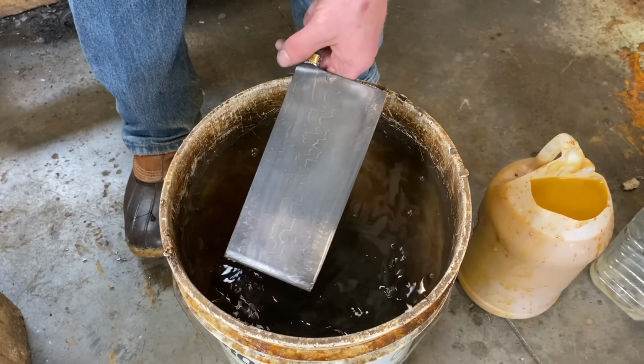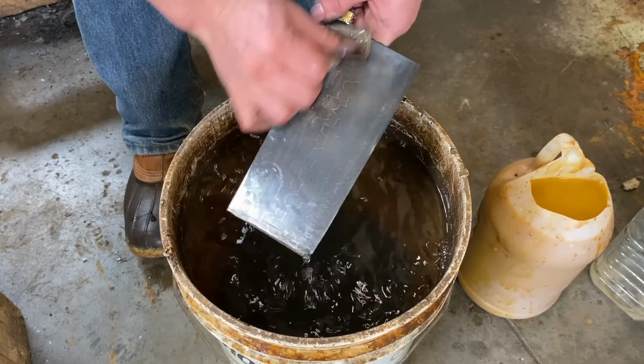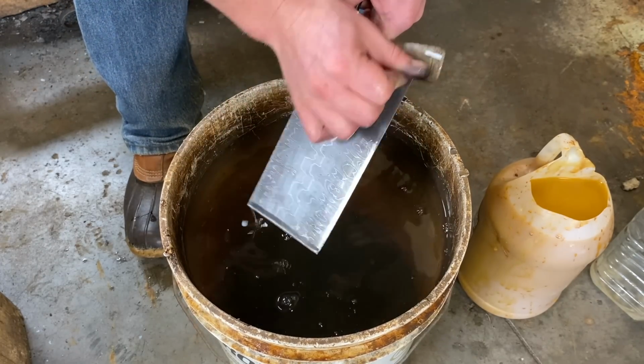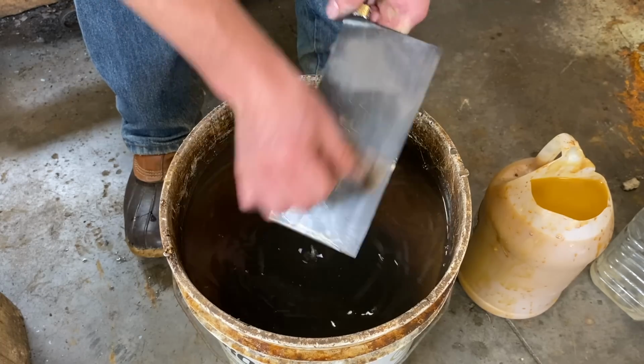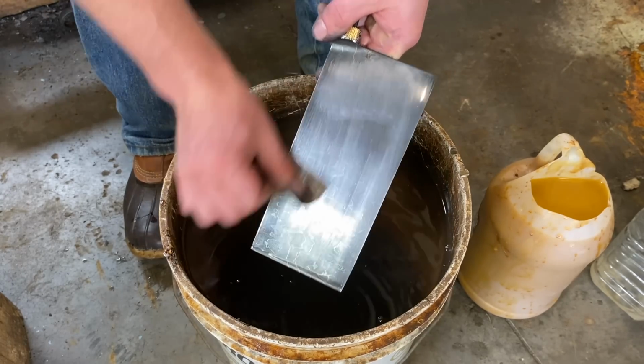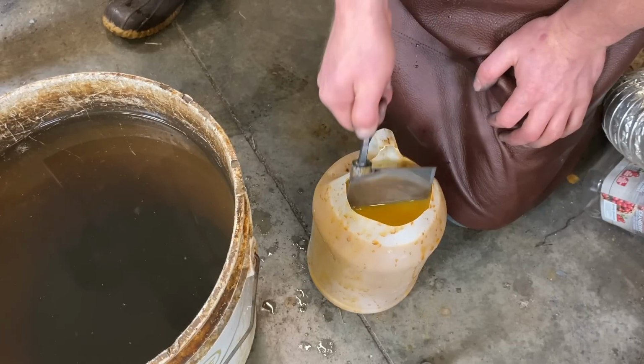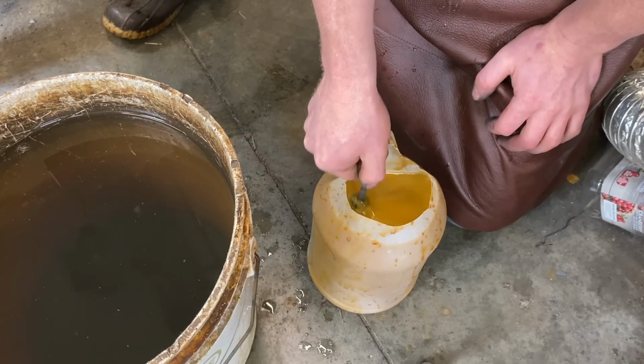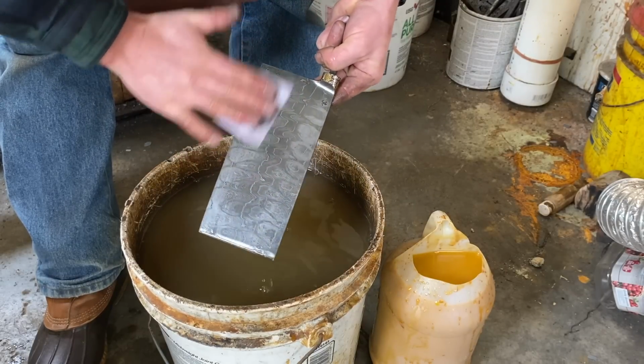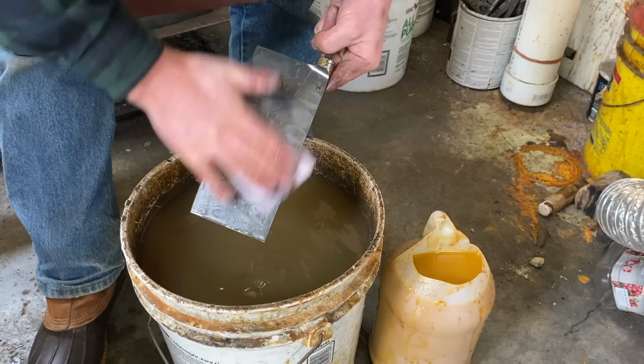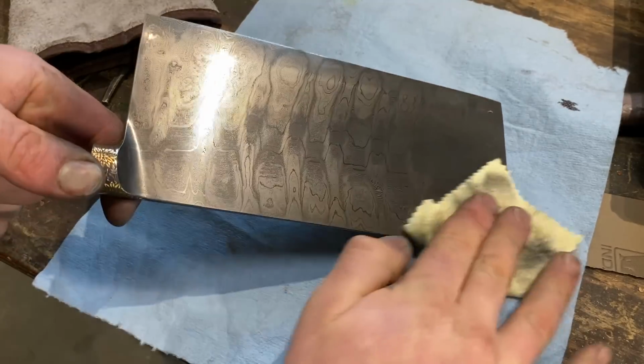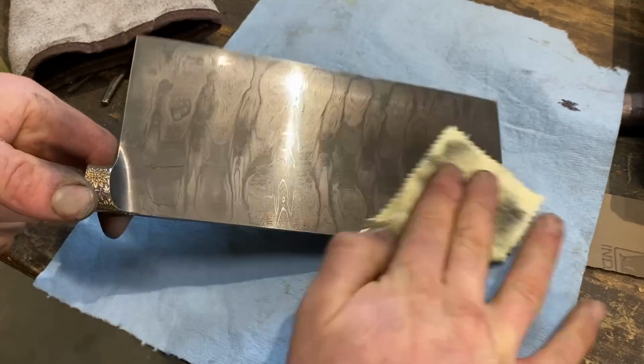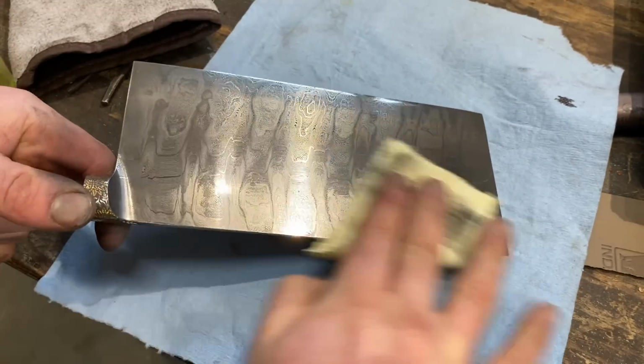I etch the knife in my ferric chloride solution for 20 to 30 minutes at a time, and then clean off the oxides with 2500 grit sandpaper. I repeat these steps until the etch is deep enough and I like the way the pattern looks. Then I neutralize the blade with baking soda, rinse it with water, rub it with alcohol, and then finally buff with sunshine cloth to get that nice shine.